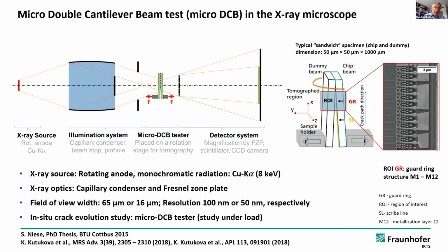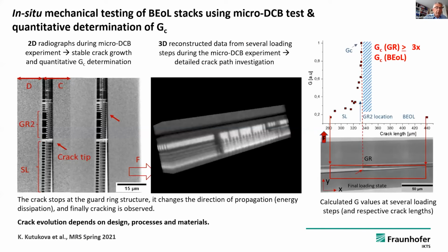The first example that I would like to show to you is the integration of a micro double cantilever beam test, a mechanical test, into an X-ray microscope, so that you are able to image the crack during crack propagation. We have done very systematic studies of crack propagation in microchips for microelectronics. This is necessary because dielectric materials that are used in leading edge microchips have a very low fracture toughness, and therefore particularly guard ring structures that stop cracks, microcracks, have to be established.